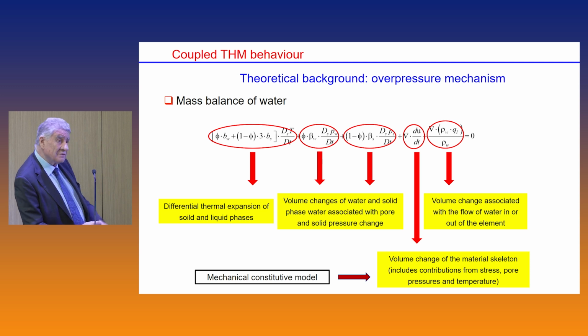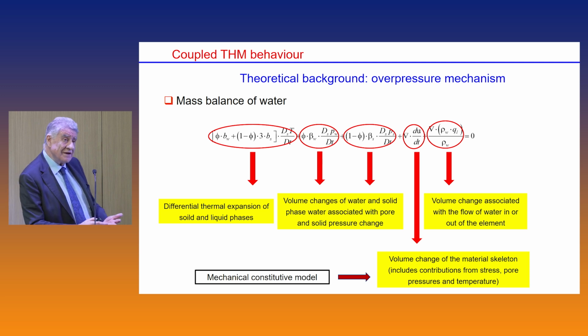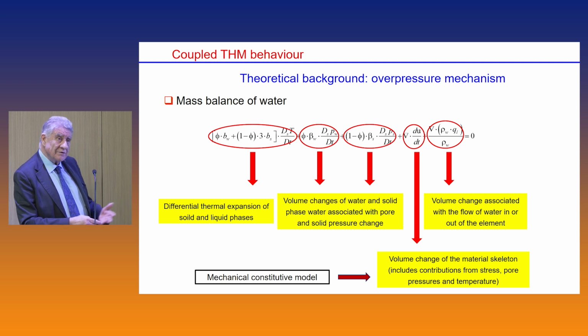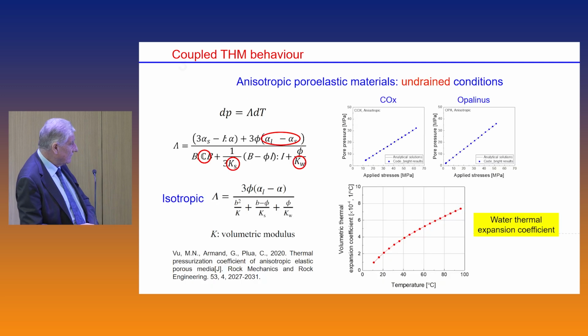The next two are the variation of the volume of these phases, not due to temperature, but other things like solid pressure and pore pressure. The fourth is the deformation of the whole skeleton, which also plays an important role. And finally, the fifth is the water coming in or out of this representative elementary volume, because the permeability is low, but it's not zero. And the interplay of all these phenomena is what gives you the pore pressure.